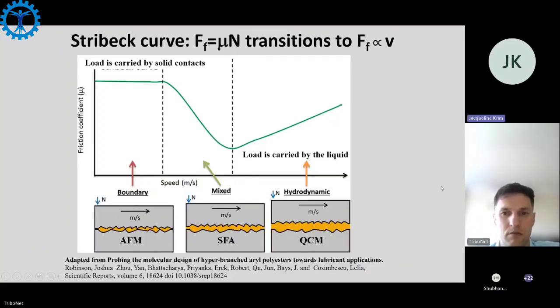So we can take a look. We carried out those experiments as a function of velocity to see which regime we were in the macroscopic scale. We thought we would be in the hydrodynamic regime because that's where it makes total sense that a QCM would match up with a macroscale measurement. But interestingly, they were in the mixed regime. So we're already seeing an effect of adding nanoparticles in a mixed regime where the liquid is providing support for the normal force. So it's already starting to lift off.